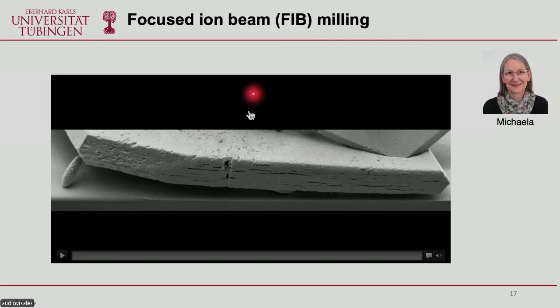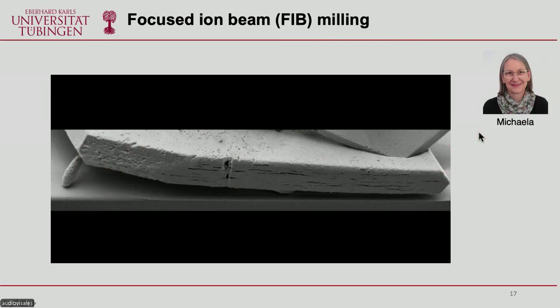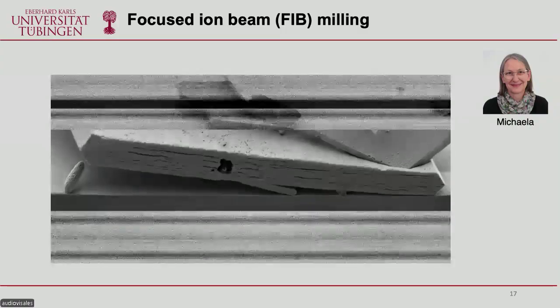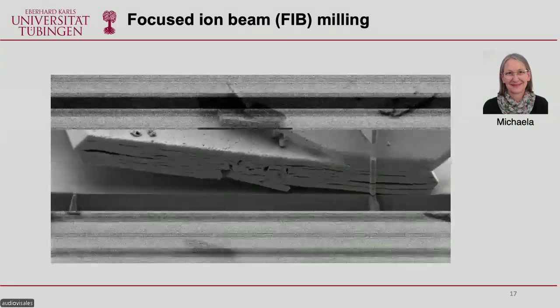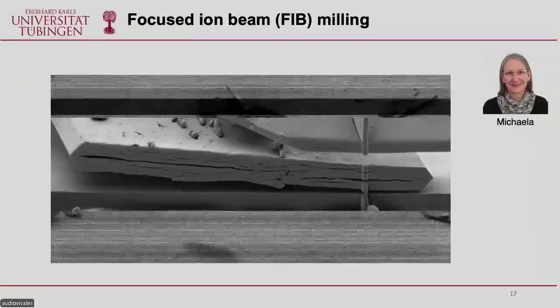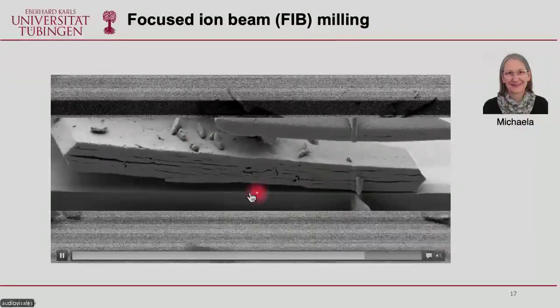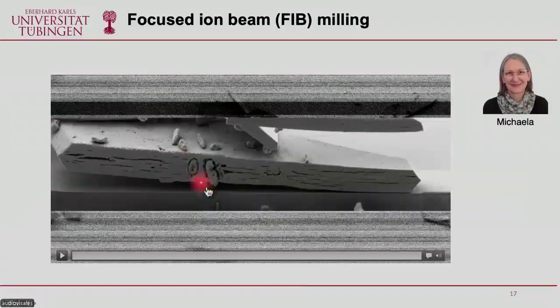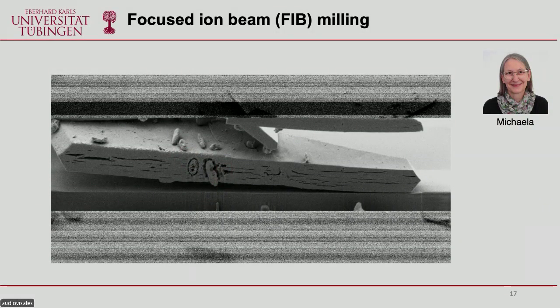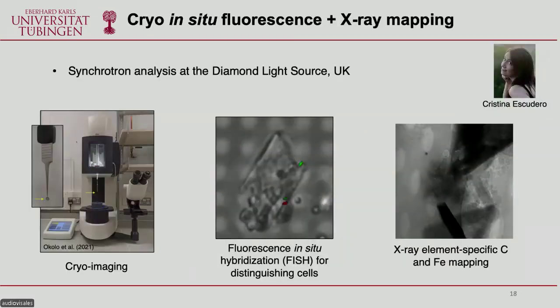And so you're going to see this video. This is a piece of vivianite, and she then uses this focused ion beam in order to cut away layer by layer, revealing what's inside the vivianite. And so here you can see that as we get down into a certain stage, we see that there are actually cells that are quite fully entombed within the vivianite. And that's great. That answers one of our questions, but we had more.